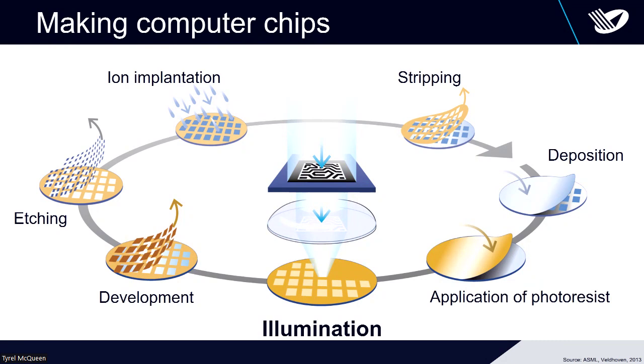That would have to be at best deep ultraviolet, 193 nanometers. In the EUV range, there are no lenses. And you imprint a pattern onto the resist material. Then it becomes either soluble or insoluble, and depending on that, you call it a positive or a negative tone resist. And afterwards, you develop it.